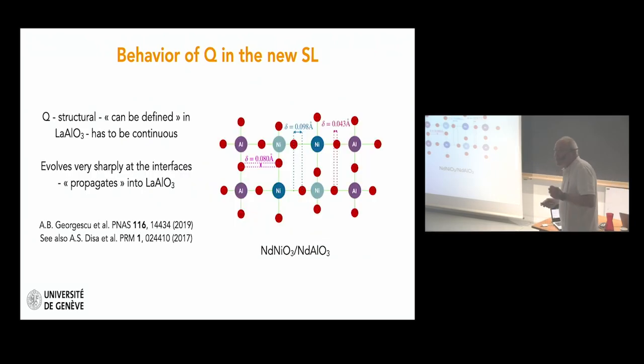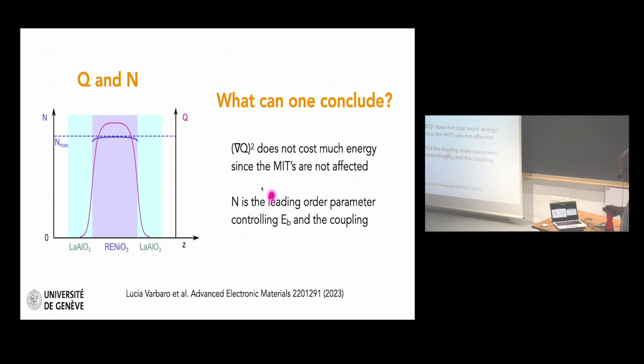But now, if we think a little more, we have our other parameter, Q, and Q is a structural parameter linking the different atoms. So Q cannot be discontinuous. Q has to be continuous. And there are calculations in a very similar system, neodymium nickelate, neodymium aluminate, which show that the distortions go very quickly to 0 in lanthanum aluminate, but do penetrate a little bit. So our picture is that in the system, the n order parameter has some value and is not bending very much, whereas the Q order parameter is doing this. But this is telling us something. This is telling us that n is the dominant order parameter for this coupling, because if it were Q, we would have a very large cost. So n is probably the leading order parameter.